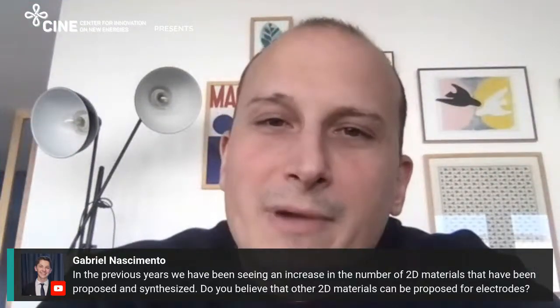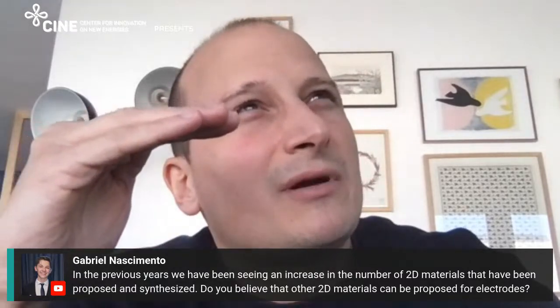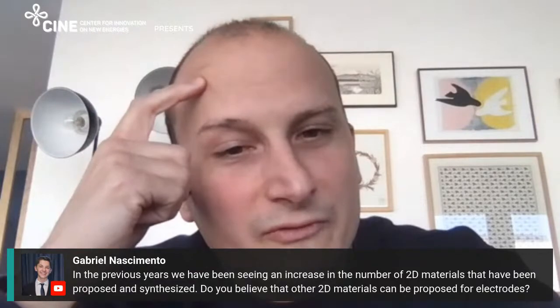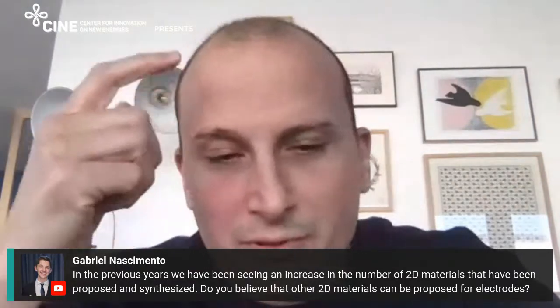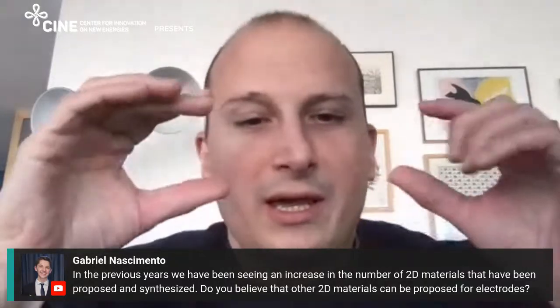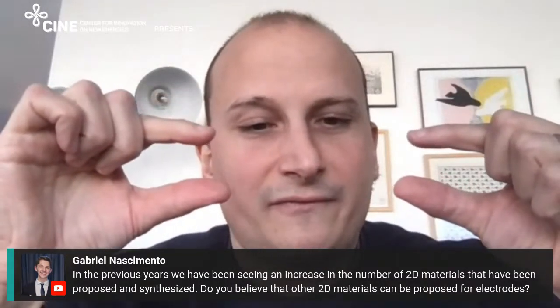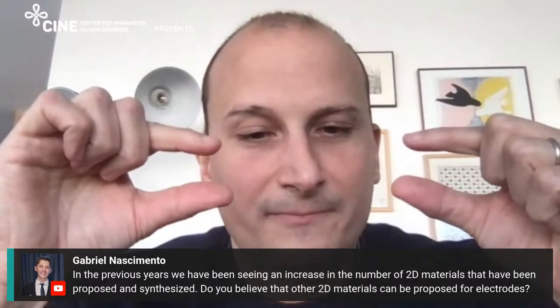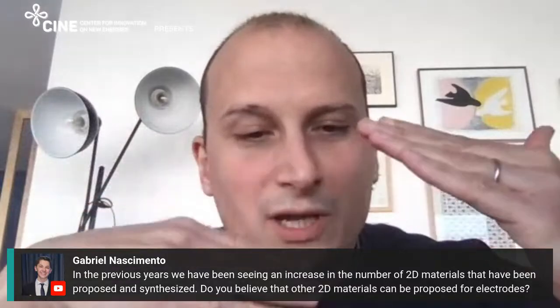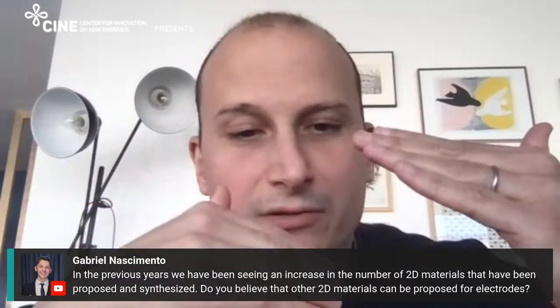So in previous years, we have been seeing an increase in the number of 2D materials that have been proposed and synthesized. Do you believe that other 2D materials can be proposed for electrodes? So clearly, the main example is MXenes. You probably heard about them. These are materials that are made from MAX phases, things like titanium aluminum carbide, and you remove the aluminum, for example, but you have a lot of other examples, and you end up with 2D materials that have very good conductivity, and they can be swelled quite easily, so you can make them porous and allow the electrolyte to go in between.